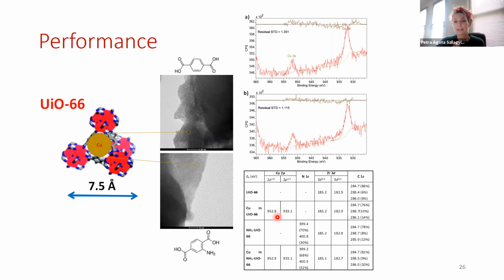Now, copper is a little bit particular. So we also looked at the nitrogen binding energy, to compare the nitrogen binding energy as observed in the empty framework with that observed in the copper-laden framework, and it was exactly the same.